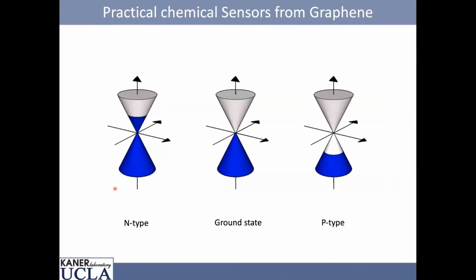Now, I want to just show you the band structure of graphene. So graphite would have a valence band and a conduction band that slightly overlap. But graphene, if it's perfect, has this Dirac cone that meets at a point. And so this is the filled valence band. This is the empty conduction band. So these are the pi orbitals that are filled, pi star that are empty.